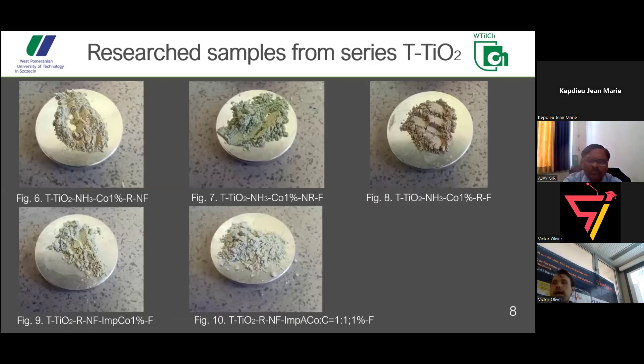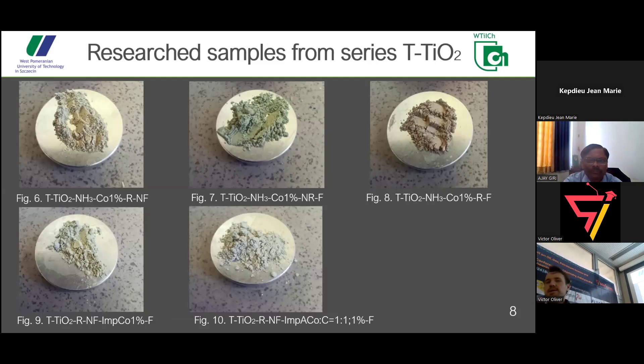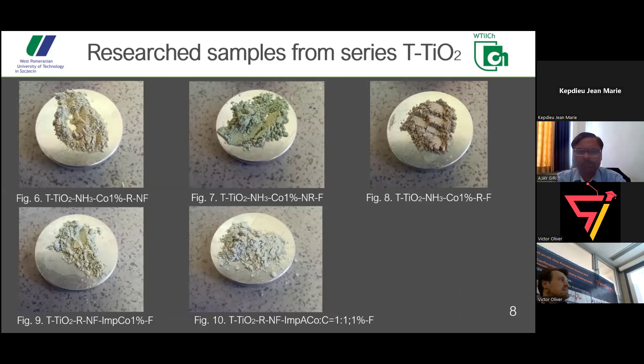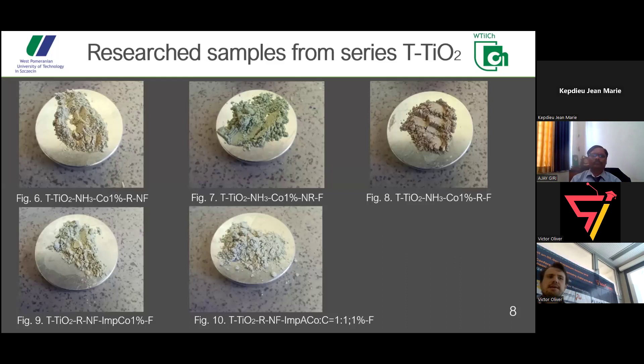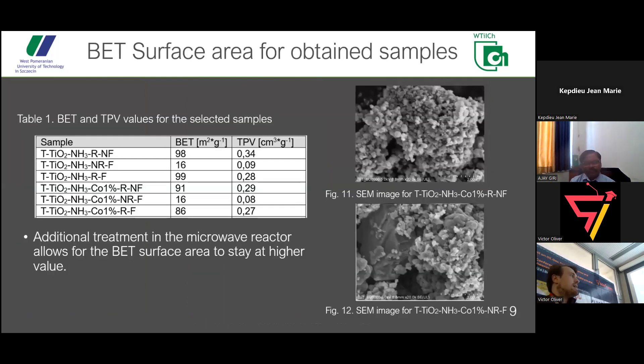This is just a visual showing how the samples look. We see that implementing cobalt to titanium dioxide doesn't really allow the titanium dioxide to stay white. Generally, photocatalysts should be as bright as possible. However, there is also a positive side, because since it becomes colorful, its absorption band shifts more into the visible range, and therefore lower-energy light can be used to excite the electrons from the valence to conduction band, which is better from a sustainability standpoint.